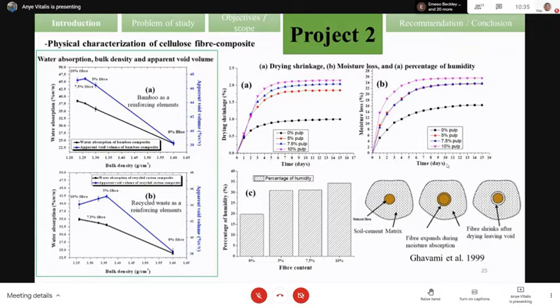Also, we study the dry shrinkage, moisture loss, and residual humidity of the fiber. We realize that the more we introduce the fiber in the matrix, we increase the dry shrinkage, we increase the moisture loss, and we also increase the percentage of humidity.